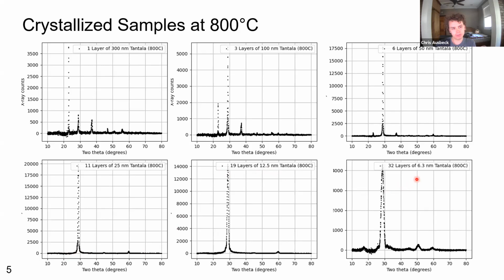So all of these samples were baked at the same temperature, at the same time, and in the same location, yet we still see differences in the crystal formations of each of these, which indicates that not only does temperature affect crystal formation, but also maybe the nanolayer size as well.